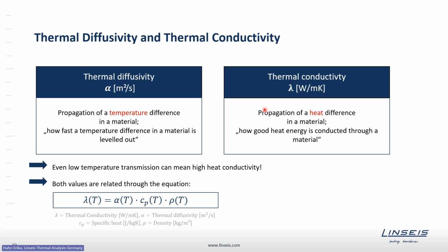So both of these properties are directly linked to each other by this equation. This is often used in practical measurements, where we measure maybe some of the properties and then calculate the other one using this relation, so that the thermal conductivity is the product of thermal diffusivity, specific heat capacity, and density. The key point here is that all of these properties are temperature dependent, so that one needs to perform temperature dependent analysis of each individual property to have the most precise result in thermal conductivity.